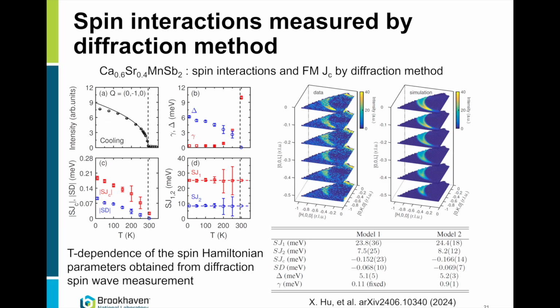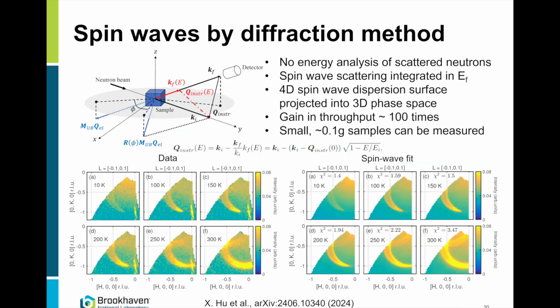The interlayer dispersion is picked up by measurements at different positions vertically on the detector, and you can see it by a naked eye as this distance from the Bragg peak. Here is a Bragg peak, magnetic Bragg peak, and the distance of the beginning of this dispersion from the magnetic Bragg peak determines the energy gap in the spin wave spectrum. Because this is a projection of a spin wave spectrum along this trajectory, it's just energy momentum conservation.